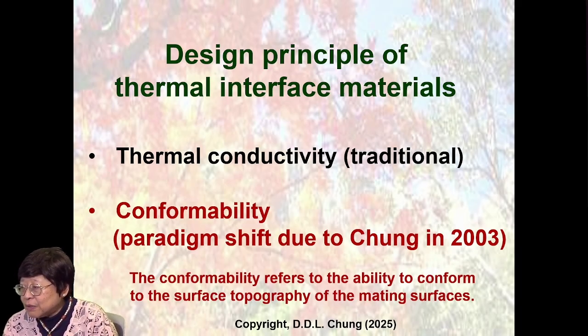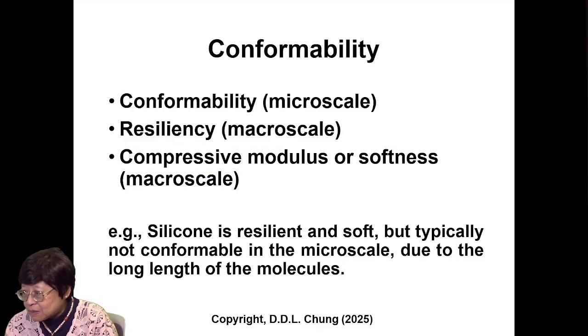The conformability refers to the ability to conform to the surface topography of the adjoining surfaces. I should stress that conformability requires micro-scale kind of conformability. That is different from macro-scale kind of resiliency or macro-scale kind of compressive modulus being low or soft. Because the little valleys in the surface topography can be in the micro scale. Silicone, for instance, is resilient and soft, but typically not conformable in the micro scale due to the long length of the molecules.